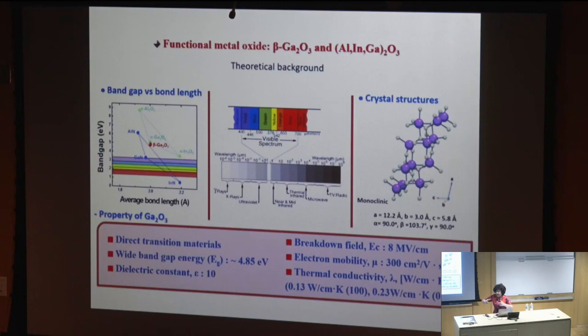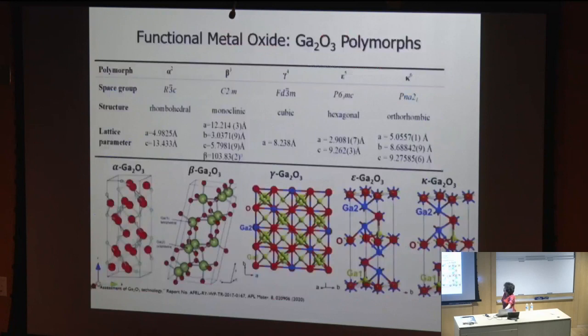But we can have substrate for that. We can have the Czochralski method to make this gallium oxide substrate. But not only that, they showed that the Baliga parameter of the gallium oxide is much higher, better than the silicon carbide and gallium nitride that they are doing. So that is excellent for the high power transistor. But again, another problem, we cannot have the p-type. So that's the reason, exactly as you can see here, that it is polymorph that has different phases, beta, gamma, and alpha, and the beta phase is the semiconductor.